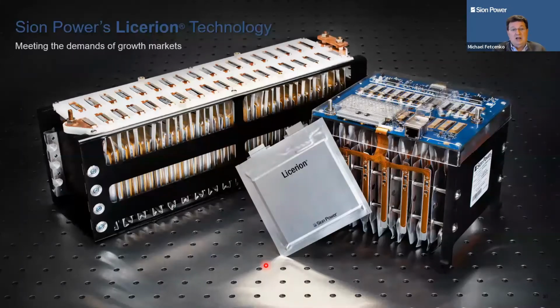What I'm working on at Sion Power is lithium metal anode with NCM cathodes. And this is a 17 amp hour pouch cell. People talk about now, some companies, I won't mention them, oh, we went from 1 layer to 4 layers and we're up to 10 layers now. We're at 70 layers. I don't want to hear about beaker stuff and I don't want to hear about PowerPoint. We've taken these 17 amp hour pouch cells and modules, fully turnkey with BMS supplied, constraints, thermal control packs that we're giving out.